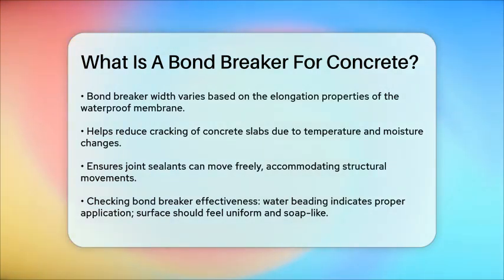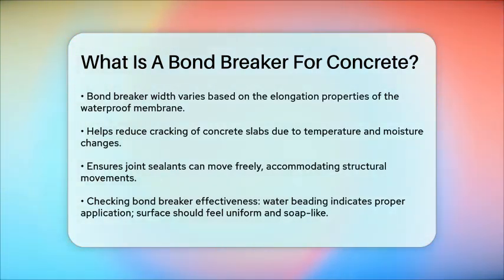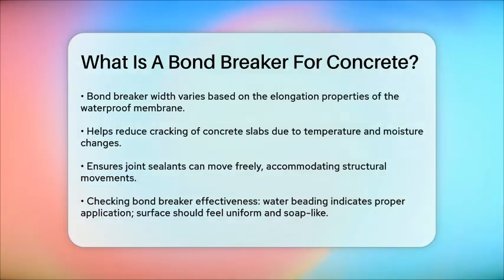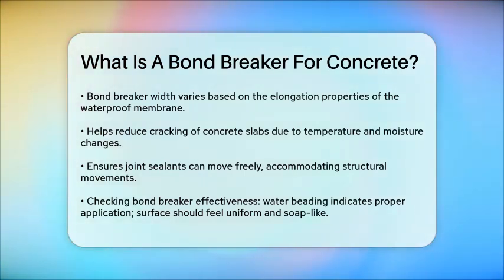To ensure the bond breaker is applied correctly, you need to check its integrity. This can be done by sprinkling water on the treated surface. If the water beads up, it indicates the bond breaker is working properly.